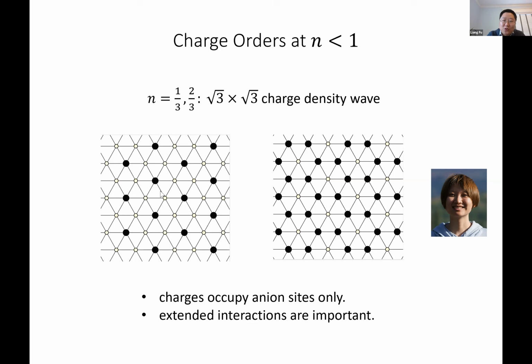And also, to understand why these density waves appear, it becomes very natural if you think about extended interactions, right? For example, at 1/3 filling, this pattern shown on the left avoids the nearest neighbor repulsion. So this is the closest packing without causing nearest neighbor repulsion. These examples show you that the extended interactions are actually important in this material.